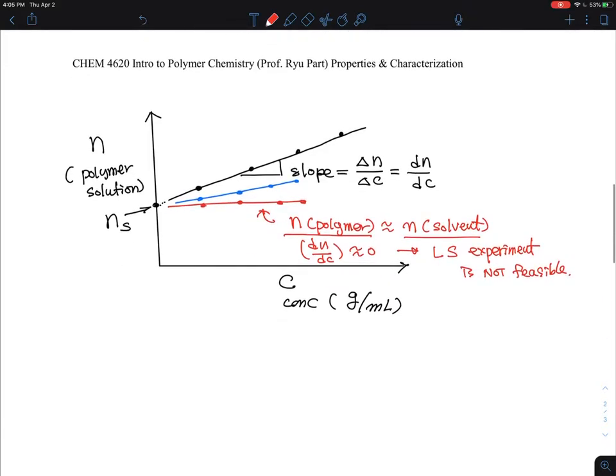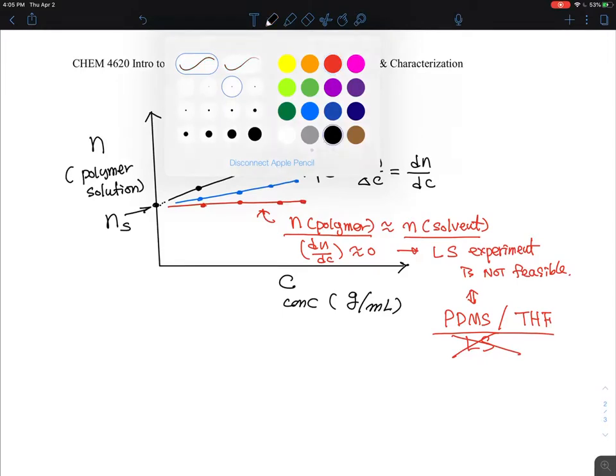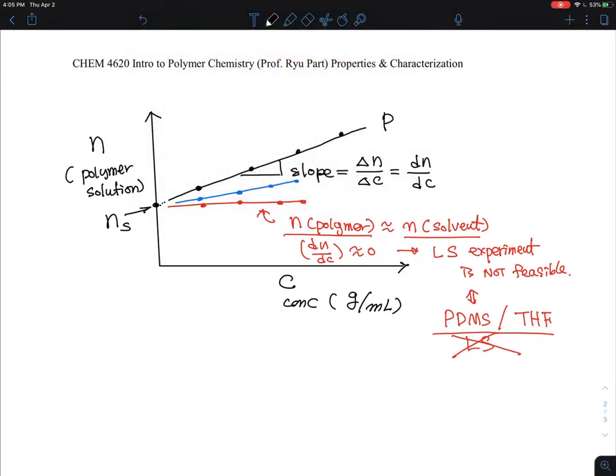And we have a very famous case where polymers and the solvent has the same refractive index. That example is PDMS in THF. PDMS is polydimethylsiloxane in THF. In light scattering, it's not possible here. So this is actually kind of a notorious system that you cannot. Essentially PDMS is invisible in THF. But other polymers that are pretty common, for example, polystyrene in THF. By the way, THF is tetrahydrofuran. It has a chemical structure that looks like this, and it has a refractive index that you guys can find out from anywhere and from the reference books.